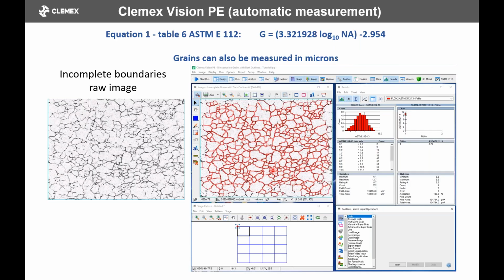Now, what I mentioned earlier is that you can detect the grain boundaries. When you end up with a good detection of the boundaries, the software will measure the grain size. Here we have two methods of measurement. This one is called an object measurement, so all the grains are measured individually. We can see grain size classes, 6.1 to 6.5, and so on, and we see the number of grains, so we have a good statistical impression of the grain distribution.